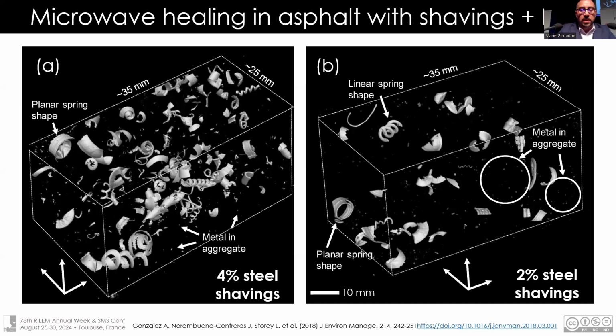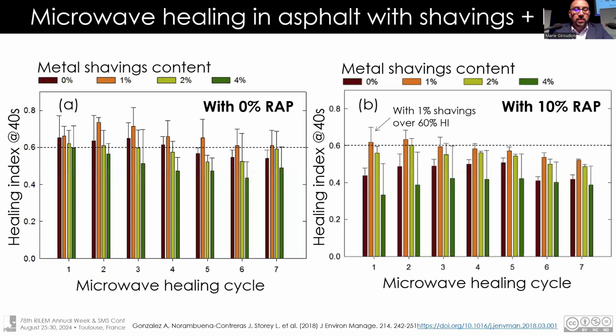Another example is to use the steel shavings from metal manufacturing inside the asphalt mixture. In design, everything is possible. All these ways can be used for asphalt healing purposes. In this case, at the same time, this additive can also be combined with the use of recycled asphalt pavement to produce a more sustainable mixture. Basically, in this research, we compared both materials: reclaimed asphalt pavement with a small addition of steel wool fiber and steel shavings to increase the temperature inside the material by using these waste materials as aggregates.